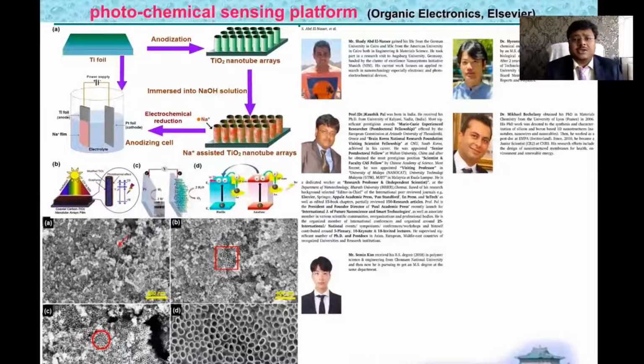And this is a sodium assisted TiO2 nanotubes array, an array for novel electrodes for a photochemical sensing platform. It is the same strategy we applied for highly aligned TiO2 nanowires and nanotubes. You can see how we aligned those things on the substrate through the anodization process and immersed them into NaOH solution, a simple, electrochemical, cost effective method, and we easily detect this photochemical sensing itself.